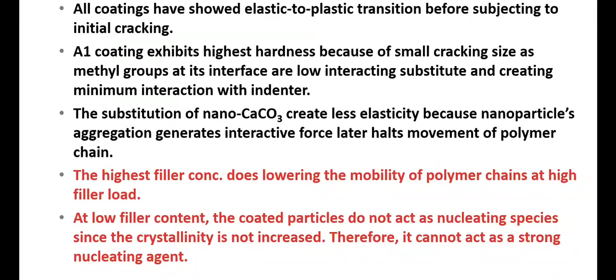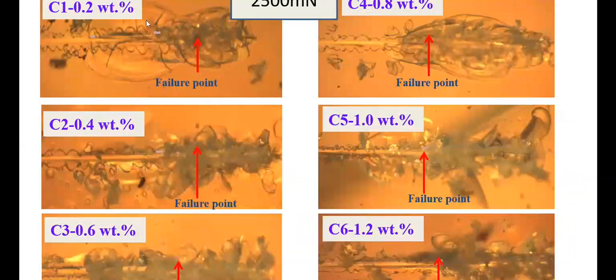So the substitution of nanocalcium carbonate creates less elasticity because nanoparticle aggregation generates interactive forces that later halt movement of the polymer chain. That is what the nanocalcium carbonate does as a filler. The highest filler concentration thus lowers the mobility of the polymer chain, and at lower filler content, the coated particles do not act as nucleation species since crystallinity is not increased. Therefore, it cannot act as a strong nucleating agent. So over here, you can see that the failure point is further out in C1, C2, C3, but it becomes shorter in C4, C5, and C6 due to increased brittleness.